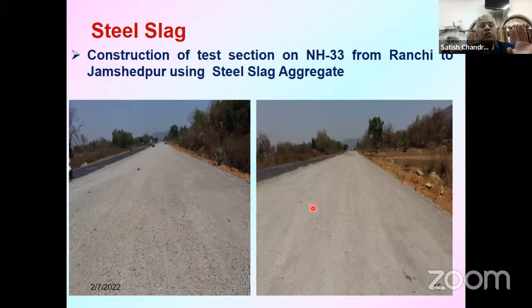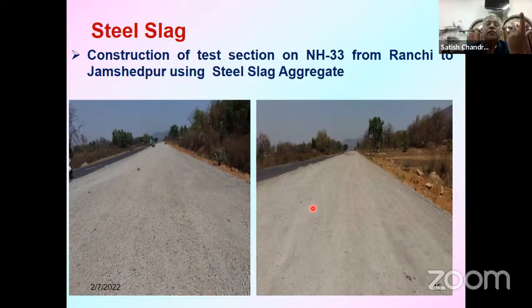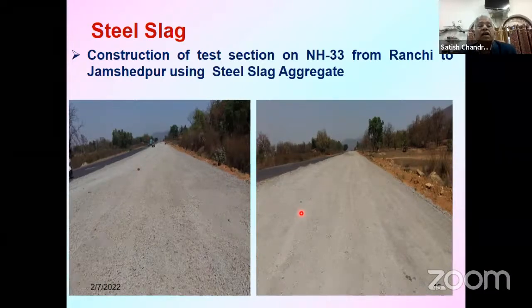It can be used in base course, in sub-base course, and in bituminous course also. The only problem when you use it in bituminous course is that these aggregates have a vesicular structure, and therefore they can absorb bitumen, and this bitumen can ooze out during hot summer, creating the problem of bleeding. Therefore the industries are now working on how to make this steel slag non-vesicular on its surface. They are changing treatment methodologies so that this aggregate can be used in the top layer also. Otherwise, it is very suitable for lower layers.